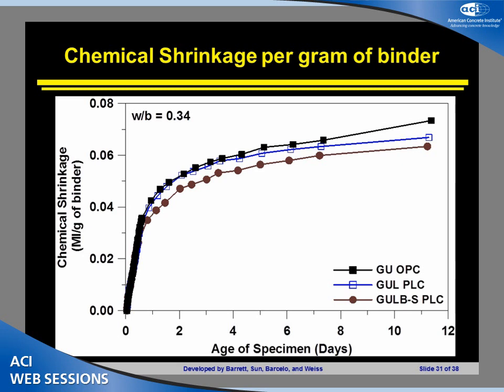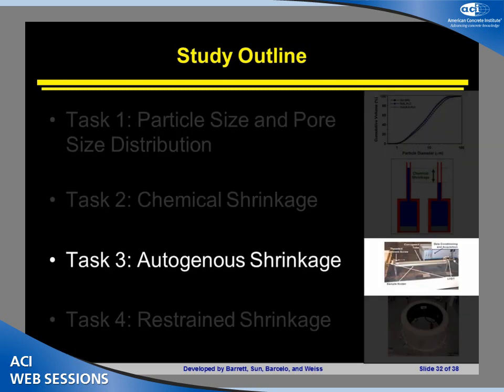The reason that this is similar, even though the system has been slightly diluted, is because we've got a more finely ground material in the system. The PLC system is more finely ground. Again, we see the slag system is a little bit slower due to the slag, but it starts to catch up as we get out toward 28 days.